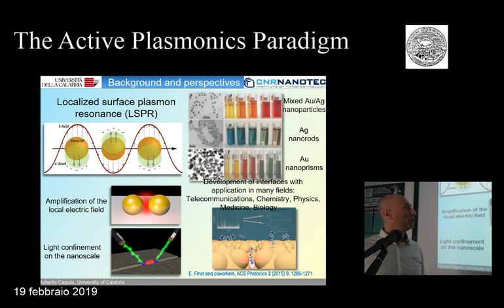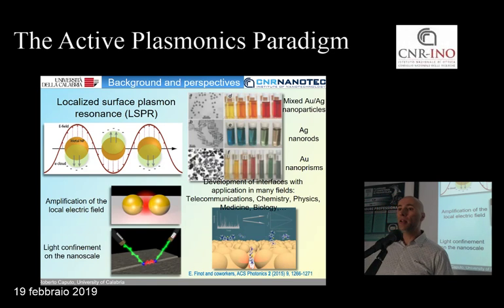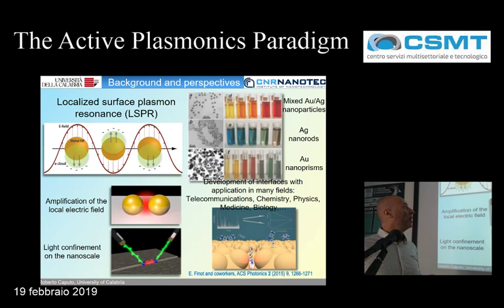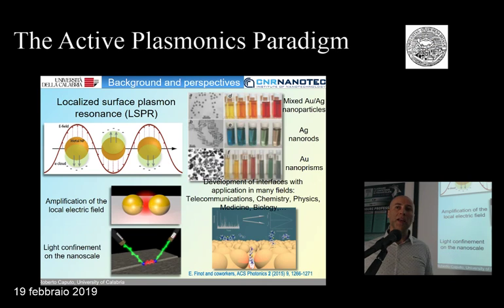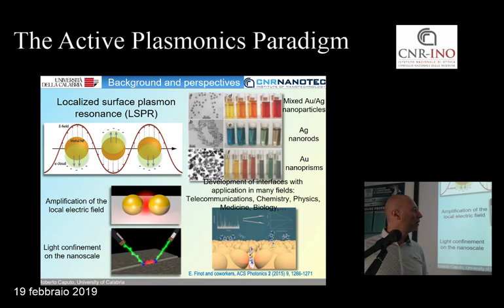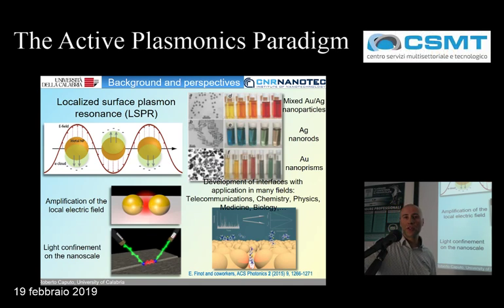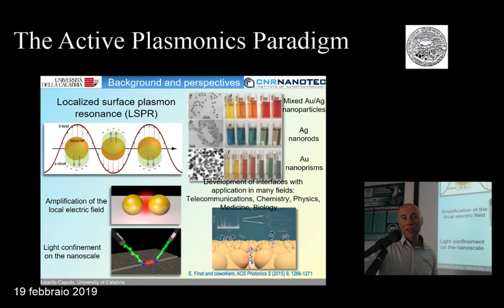So when we move more to the nanoscale, we can introduce what is plasmonic resonance. In principle, when external light illuminates nanoscale systems, the electronic cloud, the conduction cloud of the particles, tries to follow the incident light, and you have a deformation of this electronic cloud, which generates the absorption which we're speaking about. So this is very nice, because at the nanoscale, these nanoparticles have different colors depending on their size, shape, and the way they are assembled. So clusters of particles will have different colors from single particles.